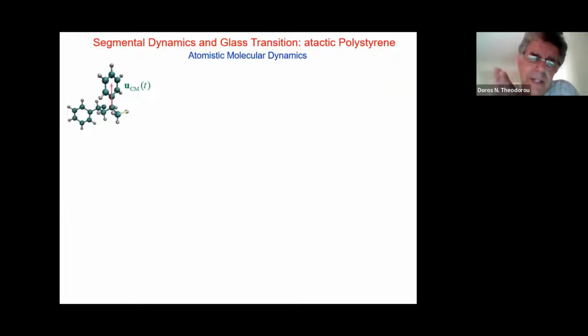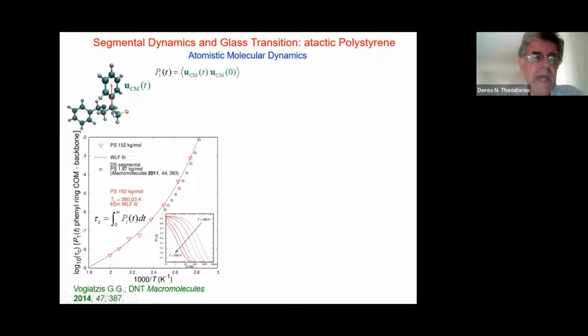And as long as you are in the melt state, you can probe the segmental dynamics by atomistic molecular dynamic simulations. For example, here we see some results from simulations of long chain polystyrene. The way we quantify the segmental dynamics is we define specific vectors affixed on the chains. For example, the vectors connecting the phenyl rings to the backbone, and we accumulate time autocorrelation functions of these vectors, which of course decay with time. This P1 of t, for example, decays with time as shown in this semi-logarithmic plot.